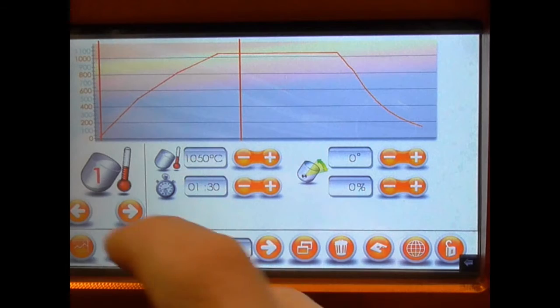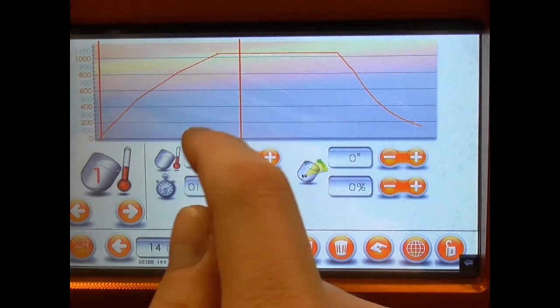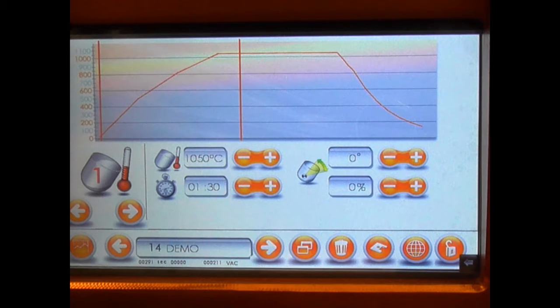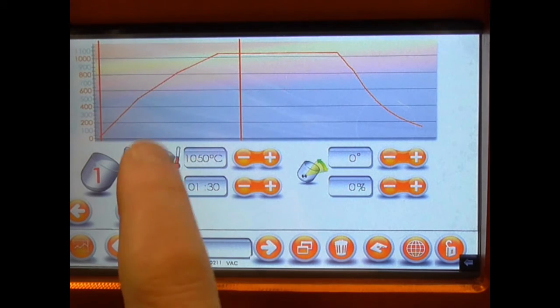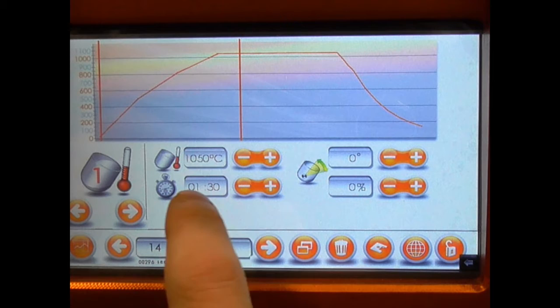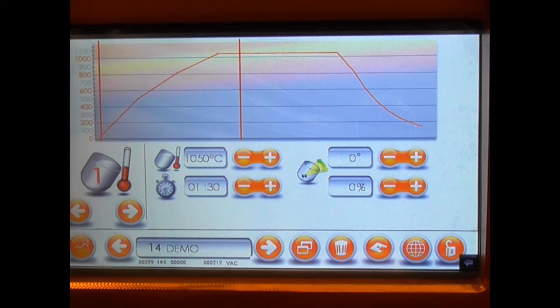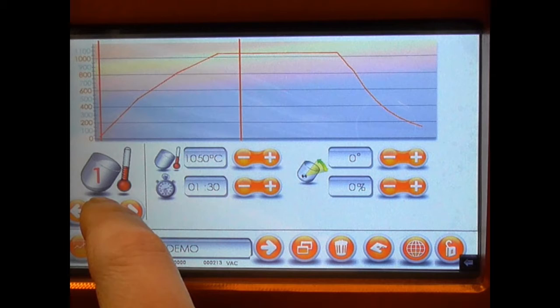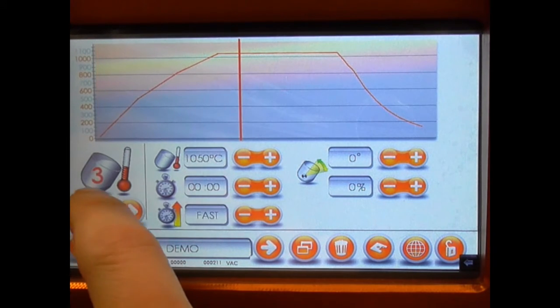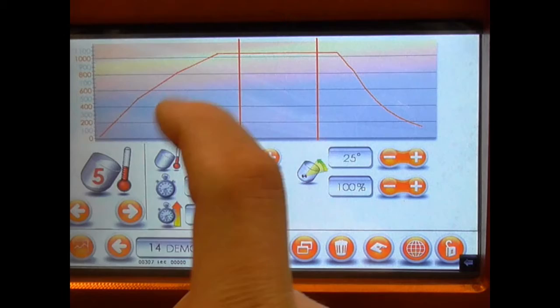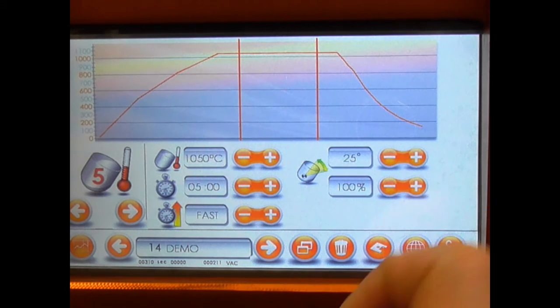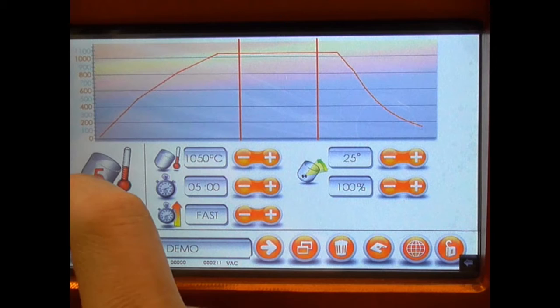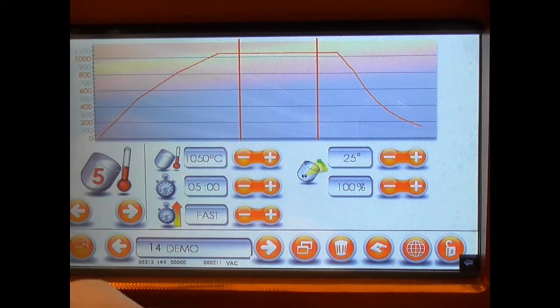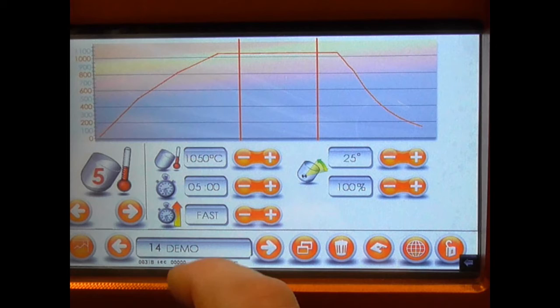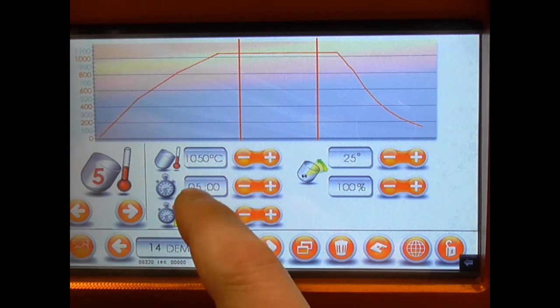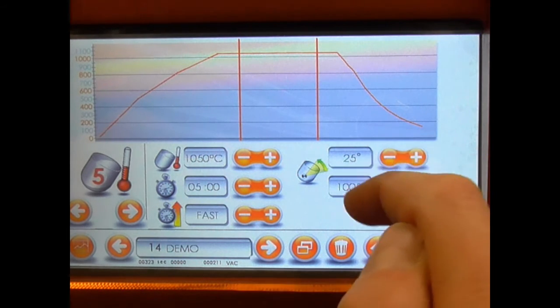So we have a simple case here where we want to reach a high temperature quickly, 1050 here. So the closed furnace will wait for you at this temperature. We will hold it for 1 minute 30, just the time for everything to melt very well before moving. You have up to 6 different heating steps where you can change temperature, time, the motion of the crucible, everything. In this case, we will typically use only 3 out of these 6 steps because we want a very simple method.